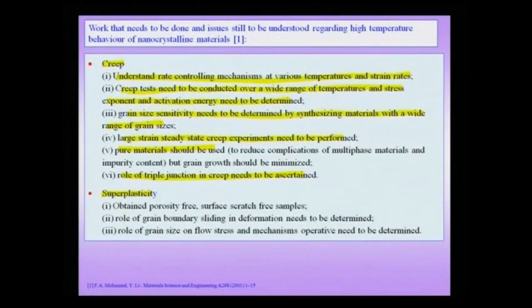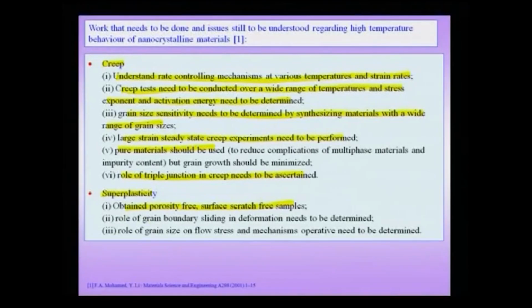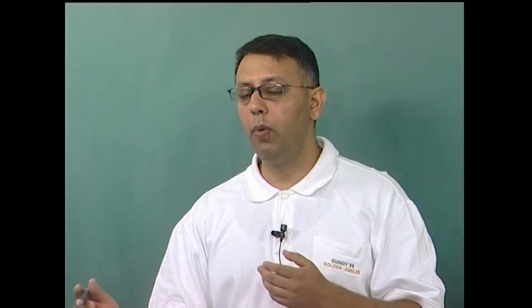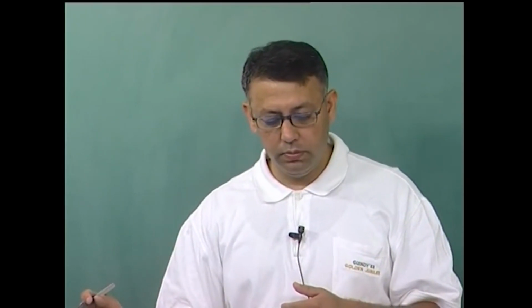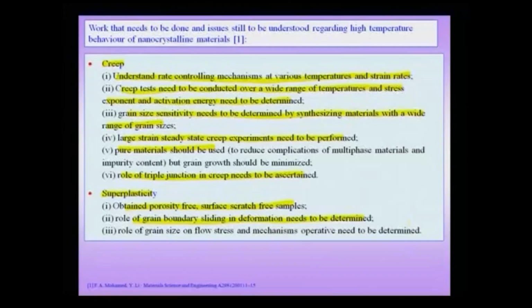In the case of superplasticity, we need to obtain porosity free samples and surface scratch free samples, because surface scratches can severely limit the overall superplasticity which I am going to get. The role of grain boundary sliding in deformation needs to be determined, that is, how much of it is actually grain boundary sliding and how much is plasticity or dislocation related mechanisms. The role of grain size on flow stress and the mechanisms operative also needs to be determined.